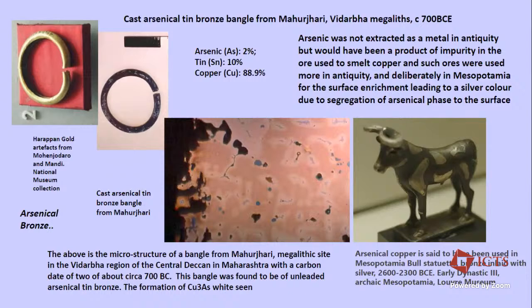And hence the effect that it would have had was that the arsenic would have actually hardened the copper. So that's why they actually preferred the arsenical bronze, because it was harder. But it's also interesting, it had another property which the Mesopotamians in particular had been able to isolate and use, which is that with about 6% of arsenic in copper, it leads to segregation. The arsenic segregates to the surface and it gives a very silvery color to the surface.